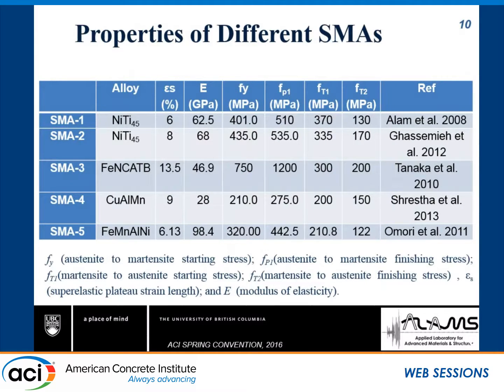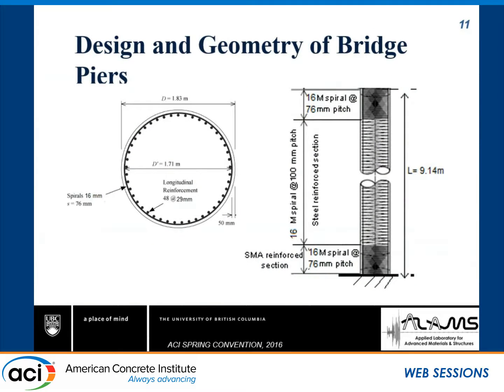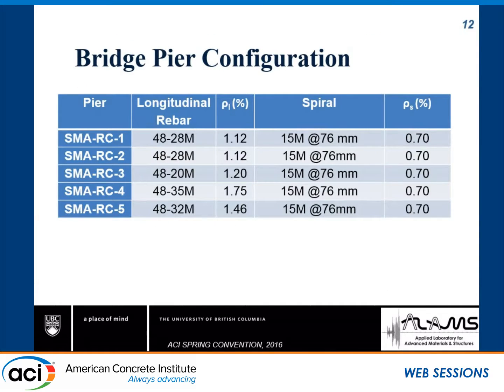We are considering five different types of SMA. The first two are nickel-titanium, the third is iron-based SMA, the fourth is copper-based SMA, and the fifth is another iron-based SMA. Looking at modulus of elasticity, copper-based SMA has much lower modulus, whereas both iron-based SMAs are similar — one is about 100 GPa (half of steel) and the other about one-quarter of steel. The bridge pier considered is about nine meters tall. All five piers are designed with the same constant diameter, same number of longitudinal bars (48), with only bar diameter differing.